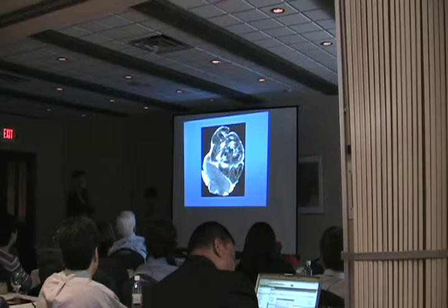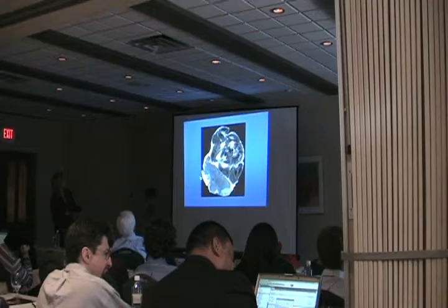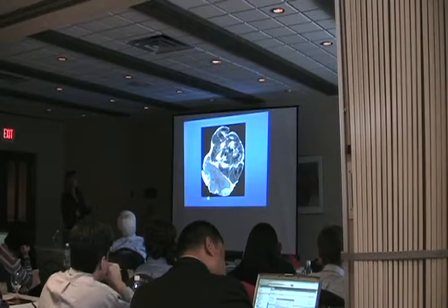Very good. So this is an actual temperature gradient image of a tumor in a mouse where nanoshells were injected and irradiated from this direction. So you can see the local photothermal heating that's built up here as a temperature map. And it turns out in this particular mouse tumor, there were some extraneous nanoshells injected back here. So you can see that the heating is incredibly localized. It's just in the microscale region where the nanoshells are embedded, and there's virtually no heating in the region between.